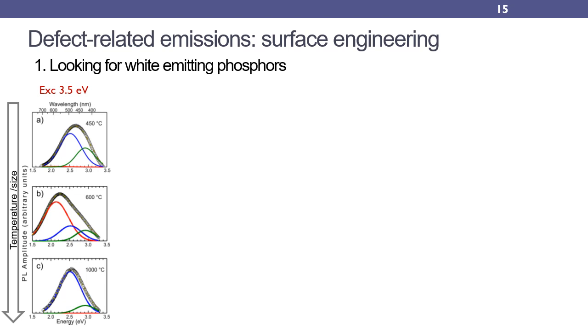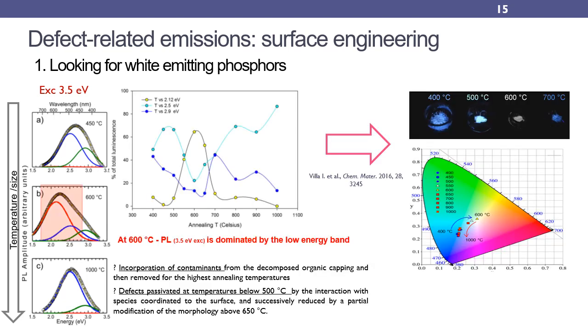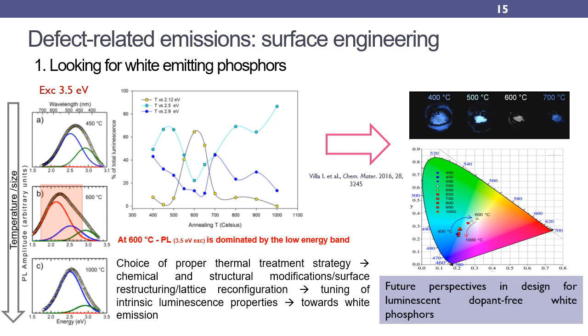In particular, nanocrystals annealed at 600 Celsius degrees under near UV display a white emission. The white emission results from the contribution of the emission at 2.2 electron volts that at 600 Celsius degrees is maximum, and it might be due to the incorporation of contaminants or the elimination of passivation on some defects. The results in this field may be a starting point for the design of optimized defect engineering strategies and the development of dopant-free white phosphors based on hafnia nanocrystals.